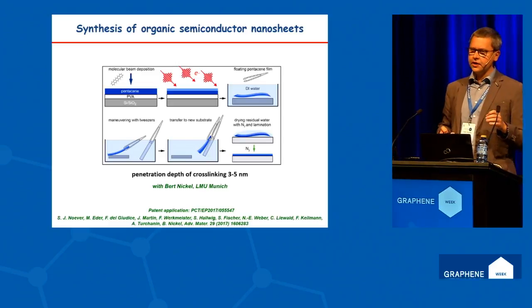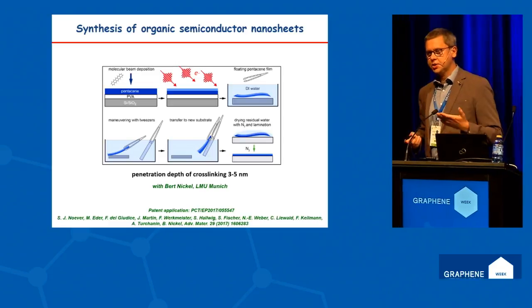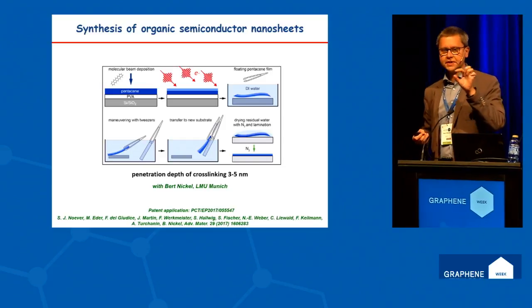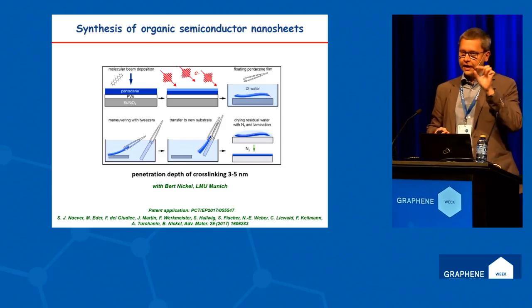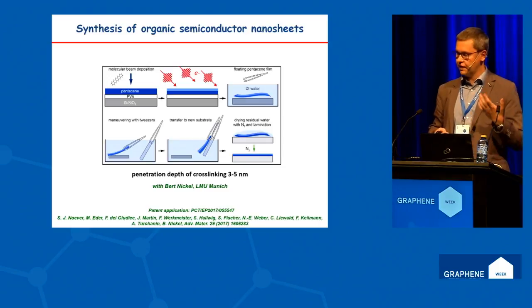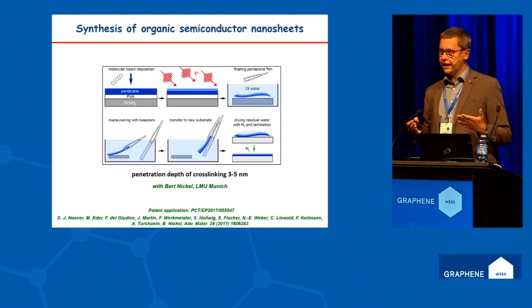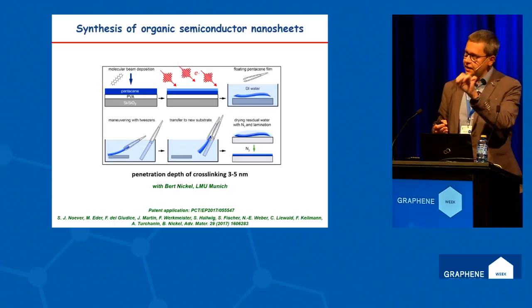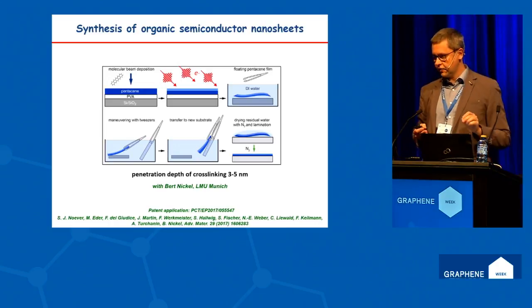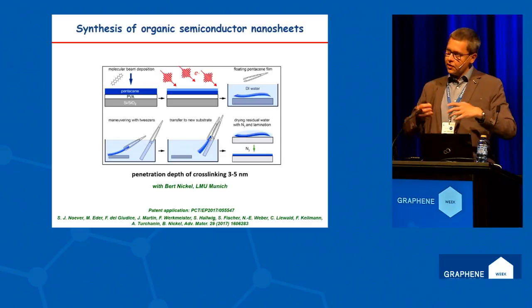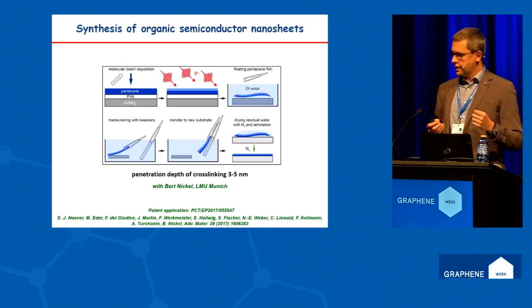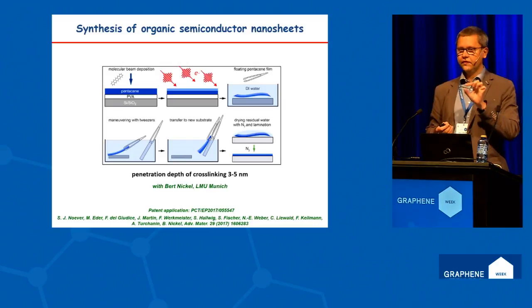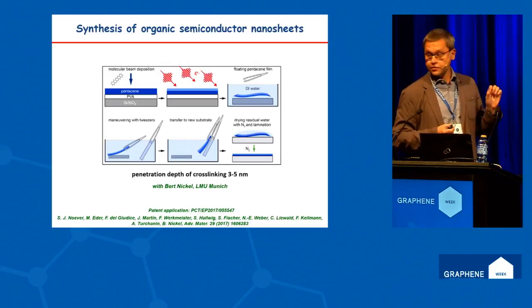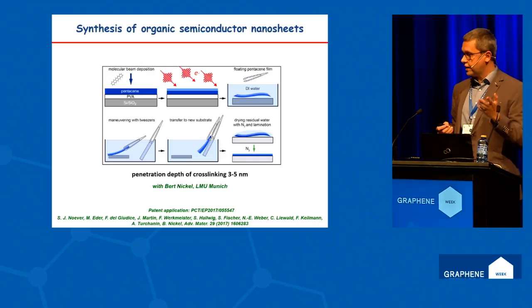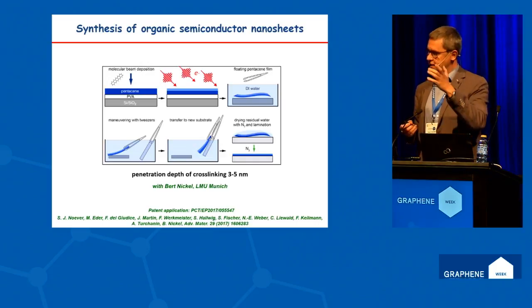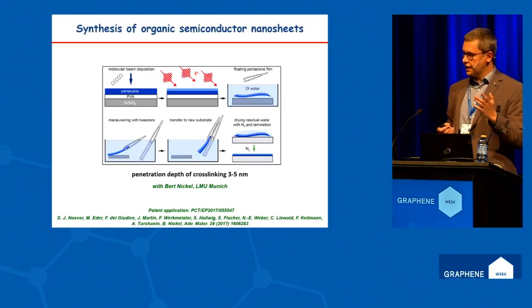So actually, we use the property of low-energy electrons that penetration depths can be precisely tuned depending on the energy of the electrons. Therefore, if we, for example, make a thin layer of organic semiconductor, we can cross-link only the topmost layer of this film while preserving the crystallinity of the remaining film. And this depth of penetration of electrons can be tuned down to 5 nanometers,